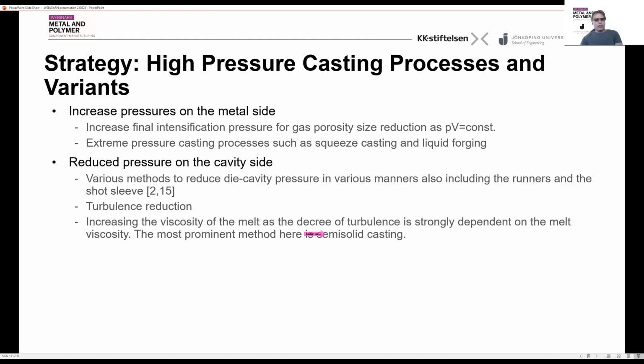So, of course, talking about these, all the low pressure die casting processes, they are for normally larger car parts like wheels and such, and they have moderate productivity. If you really want to have a higher productivity, you need to use high pressure die casting. And high pressure die casting is essentially working in a way where you, instead of pressurizing the furnace compartment, you pressurize the melt directly with a piston. So that means that instead of working with the furnace, you have now a hydraulic system, and you can increase the pressure significantly. So the new variant we have here is really to work with the melt side pressure. And that means that you can squeeze and reduce the size of porosity.